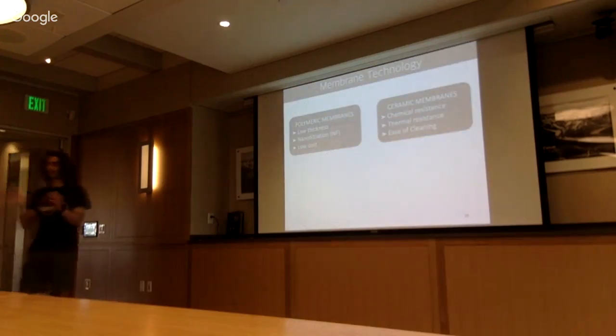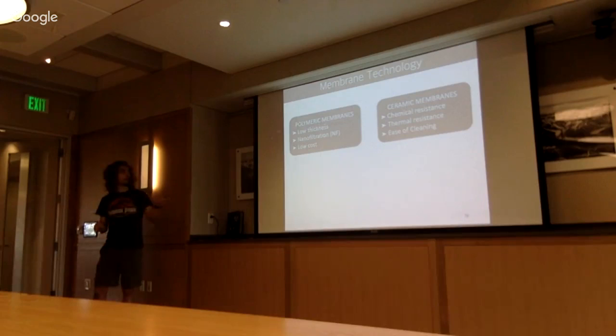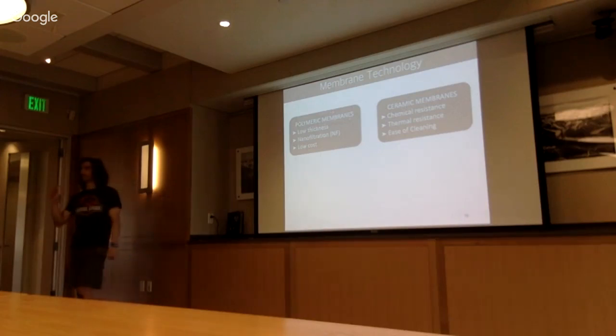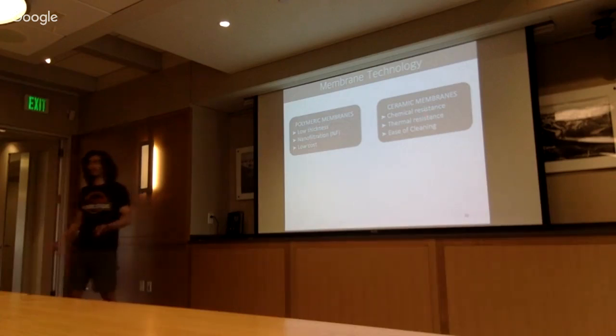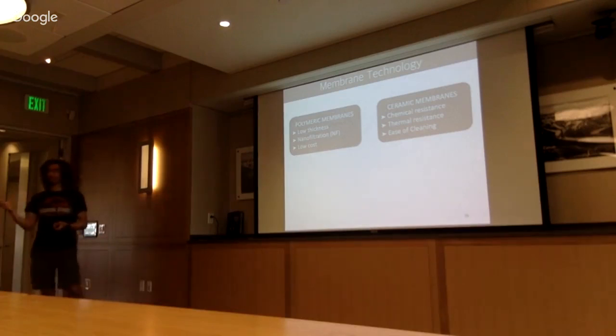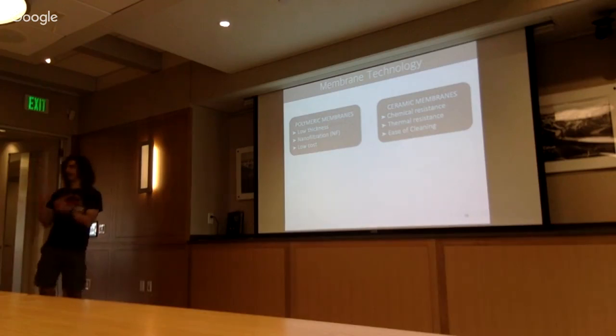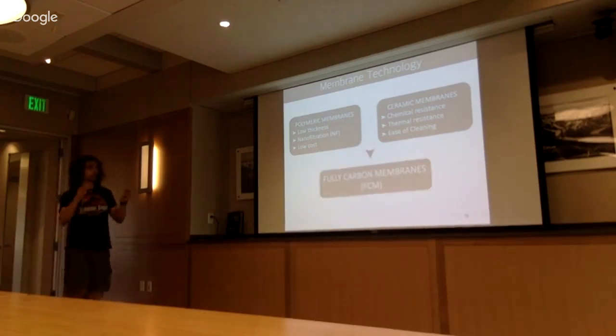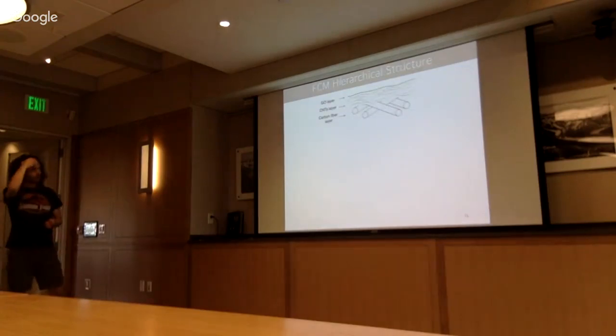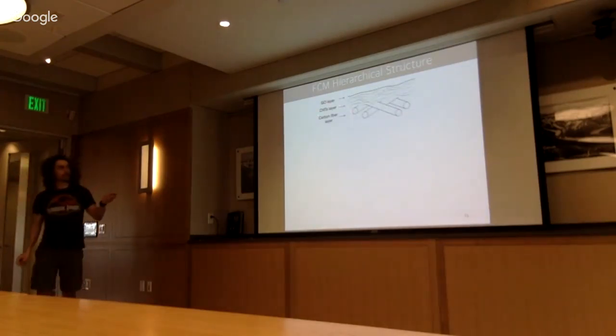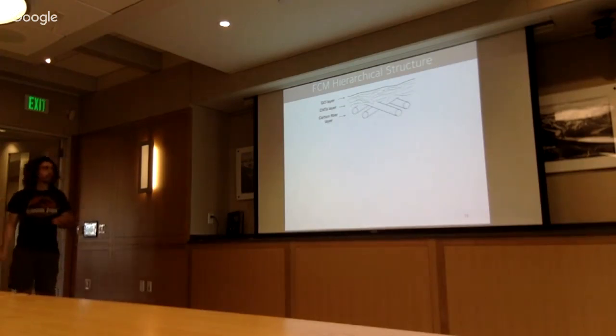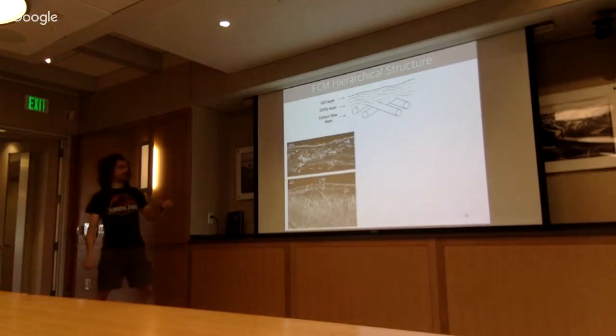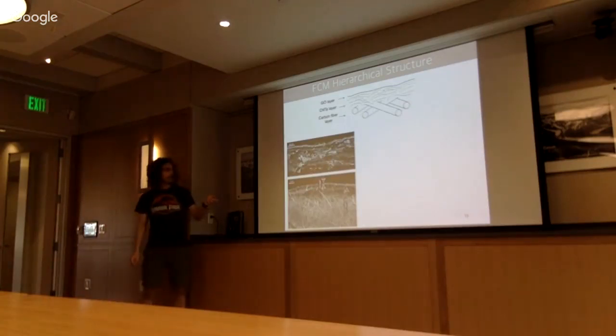And moreover, the membrane technology field is split. On one side, you have the polymeric membranes, which have low thickness, the ability to operate in the nanofiltration regime, and low cost. And on the other side, you have ceramic membranes, which have high chemical resistance, thermal resistance, and also ease of cleaning. So when we combine and make this fully carbon membrane, polymer-free, we just want to try to combine the main advantages of the two fields. So let's see how we did that. Instead of using a polymeric support, we use a support made of a carbon fiber layer and carbon nanotube layers. And here you see a cross-sectional image of the membrane. It's about half of a millimeter, and it's mainly just the thickness of the carbon fiber.